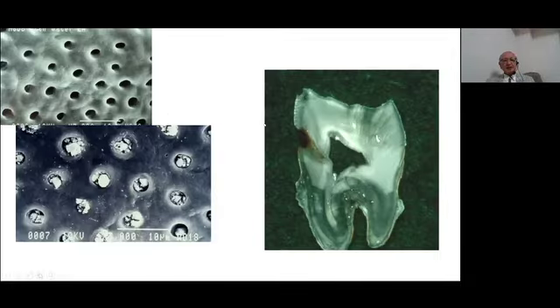Okay, this is another specimen. You can see that this is cervical caries. At the bottom of this cavity, transparent dentin is created and also reparative dentin is created. In this case, the cavity preparation shape is like this. And this is the SEM of the intact dentin surface after the phosphoric acid etching. The SEM looks very excellent for bonding.